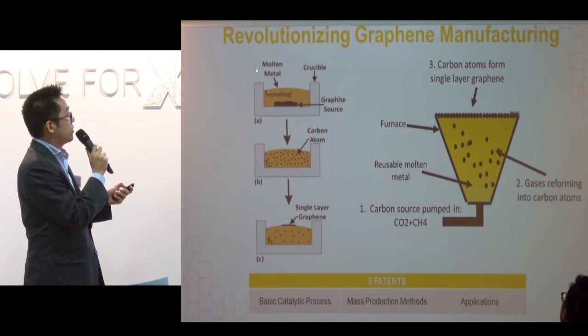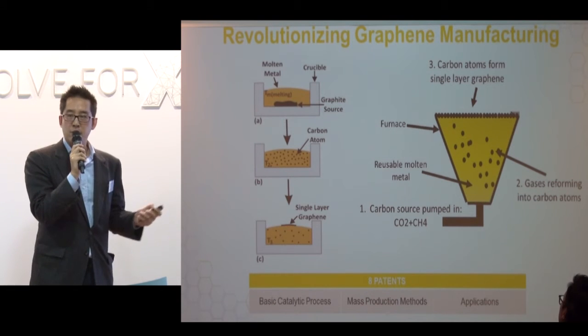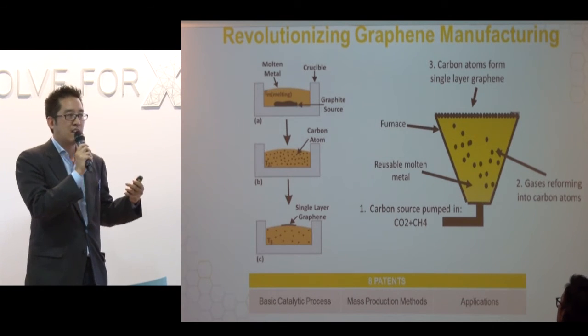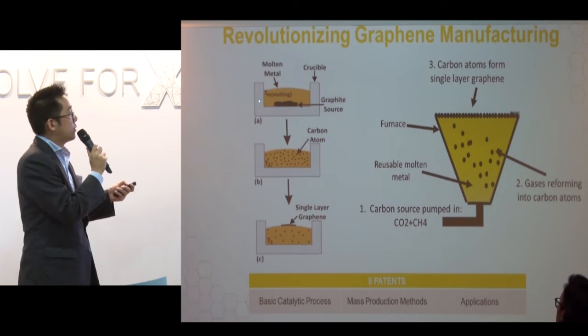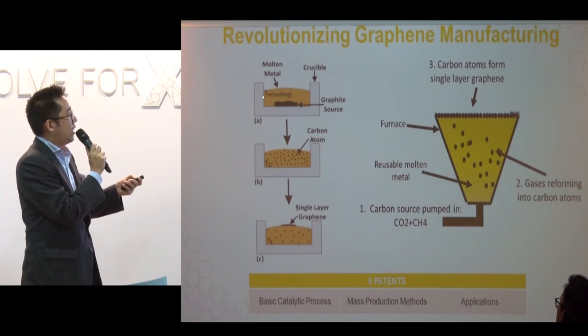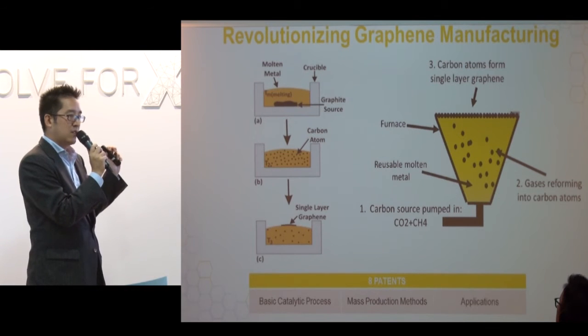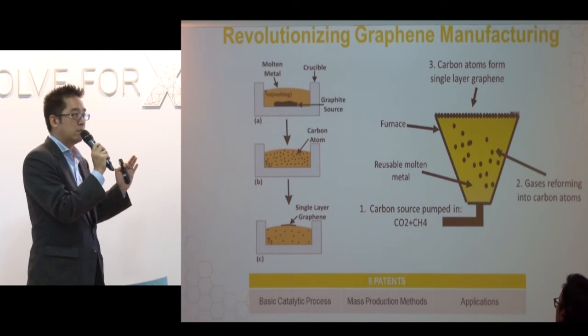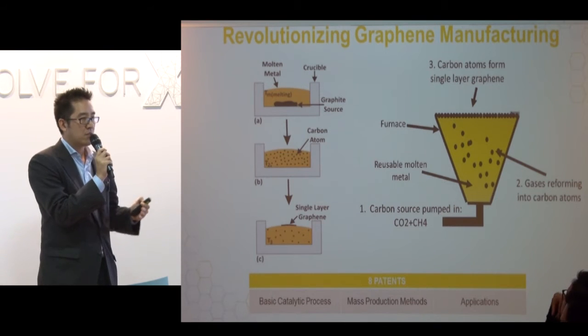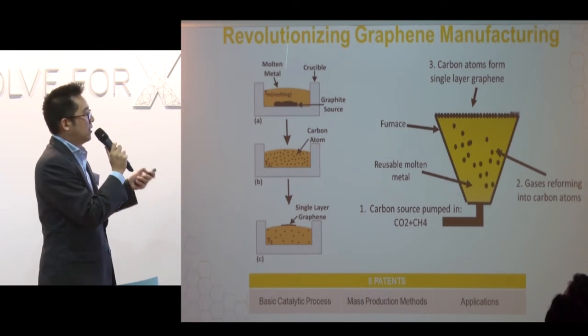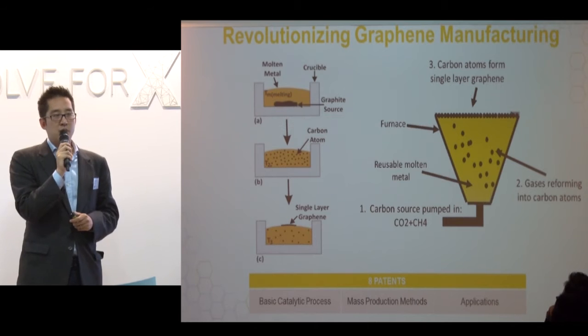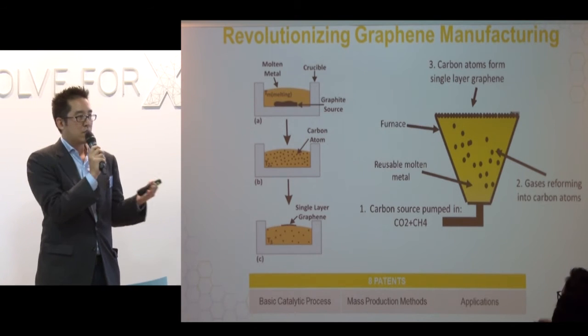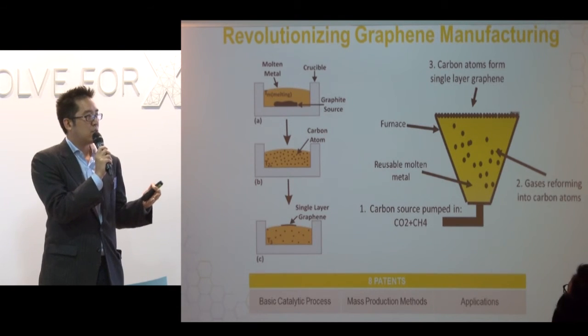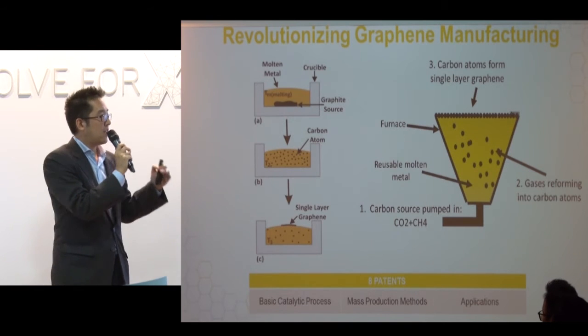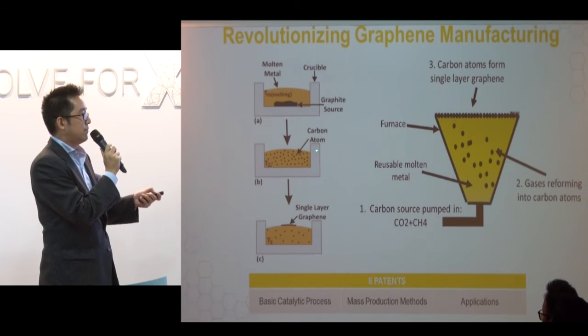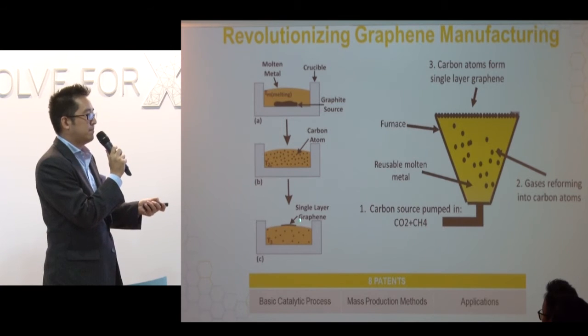Okay, so what we do is we have a crucible. Any sort of vacuum furnace will do. You can think of it as a pot that heats up. And then what we do is we put our alloy in this, which is just a simple combination of nickel and iron. We melt it into a solvent, so it's just liquid, and then we dump any sort of carbon source into it. The carbon will dissolve into the solvent and then will re-precipitate itself as graphene. And that graphene will naturally flow to the top.